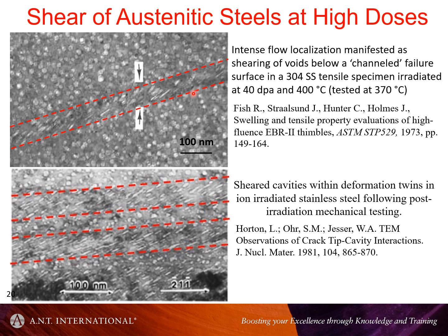their steel samples, but they also noticed in the same sample that they had these bands, if you like, of sheared cavities. Now, you can jump to conclusions and say, they're related, or you can not jump to conclusions and say, why are they related? So then the intellectual leap came from, well, look at the amount of shearing: we got like 100% here, which would have been a 45-degree angle as opposed to a 35-degree angle.